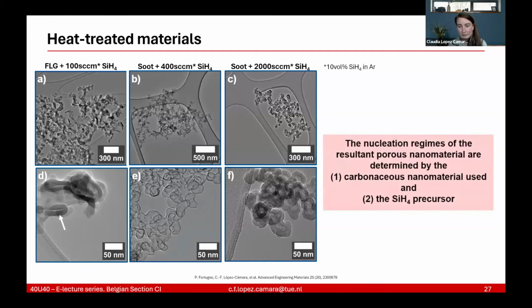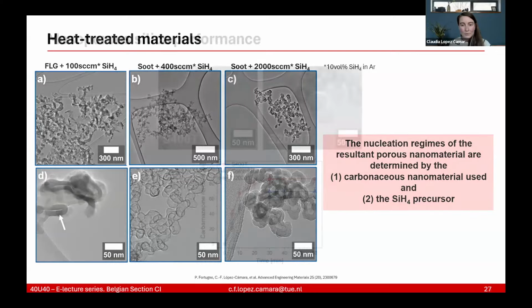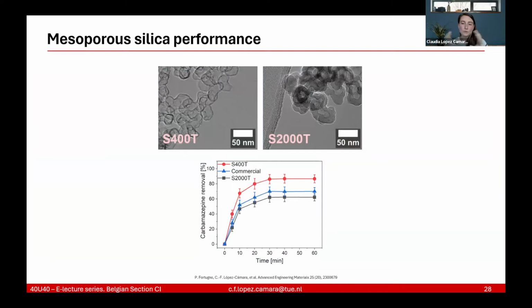And something that I found, to clarify, yes, we saw that the nucleation regimes of the resultant porous nanomaterial are determined by the carbonaceous nanomaterial, which was basically telling us that if you get graphene or you get soot, you can create different shapes. And by the silane precursor, because if you use more silane, you get thicker walls. But something that was really nice to see as well is that, farther than a new templating method, is this useful? We saw that using the soot as a baseline and coating it, and then of course getting rid of the soot in the oven, we got a